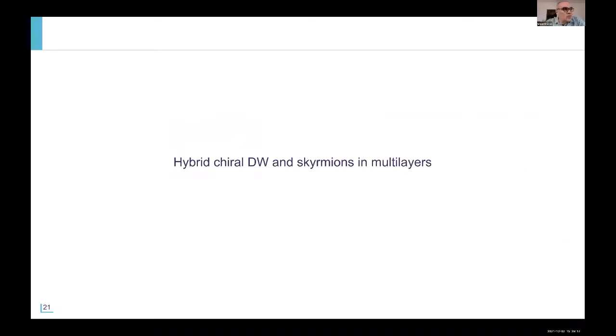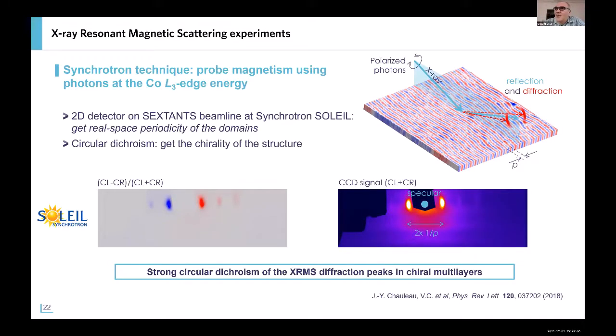Okay, now I want to go a bit beyond, because talking about the role of the dipolar interaction. In fact, we use not only thin films, but also multilayers in order to stabilize the skyrmion and increase the stability, but there is a price to pay for that. It is that the dipolar interaction, the dipolar field between layers, is not negligible, and it brings some new features in this spin texture that can be stabilized.